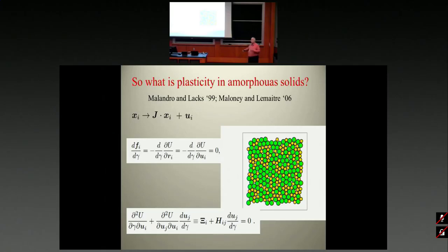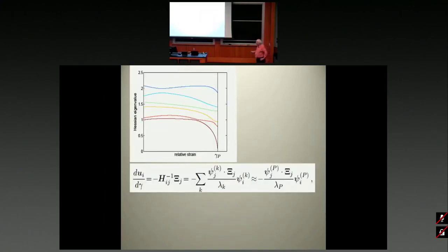So what is the situation? The situation is really very interesting. Always when you start in equilibrium, before you strain, it turns out that all your eigenvalues are positive. The system is stable. Okay? So here is an example of the eigenvalues of the Hessian matrix as a function of the relative strain. And you see, you start, they're all positive. Now you increase the strain. Many of them don't care. They change a little, but nothing catastrophic. But every now and then, catastrophe. An eigenvalue, boop, goes to zero. This is an instability. This is a plastic event. This is where something interesting happens.